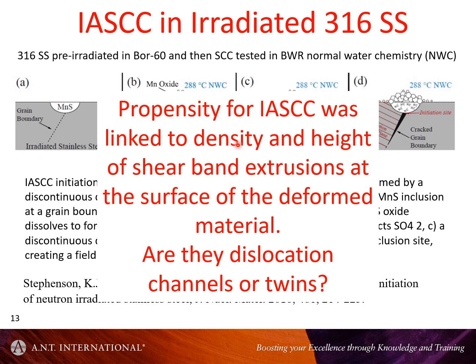And the idea is that these channels, what are ambiguously called channels, are sites for increased stress, although it's not clear exactly what stress we're talking about. Although, if you have a planar band of dislocations and there's a pileup, then you do get some enhancement of the stress, of the shear stress at the point where the pileup happens.